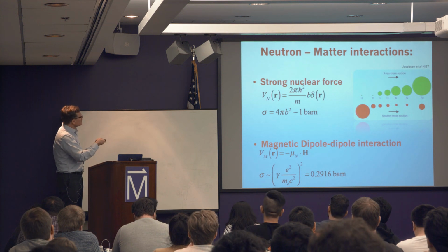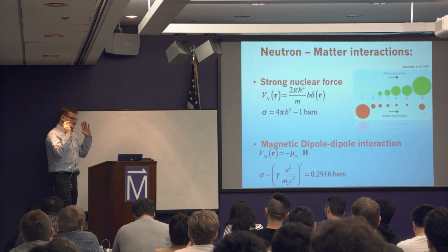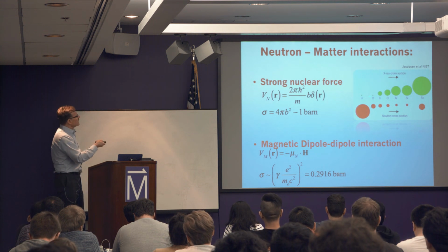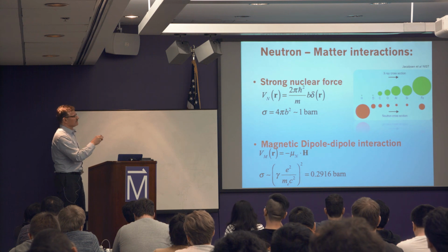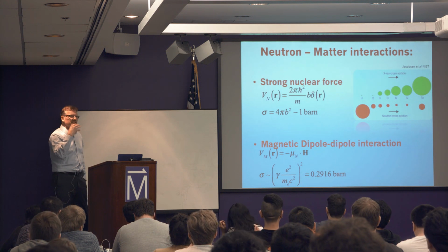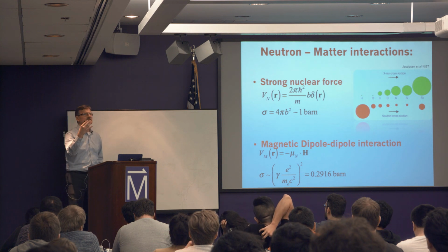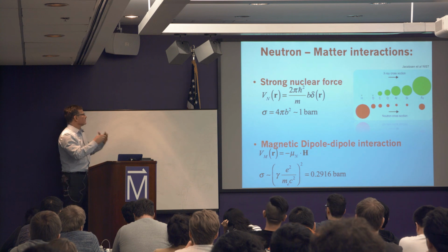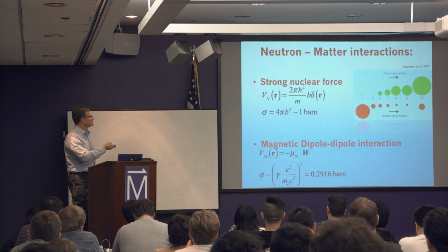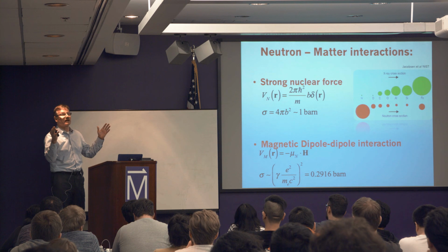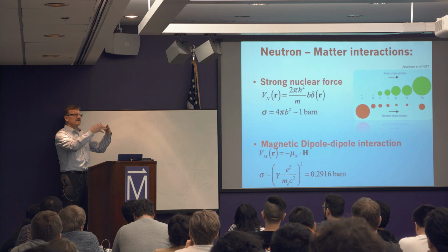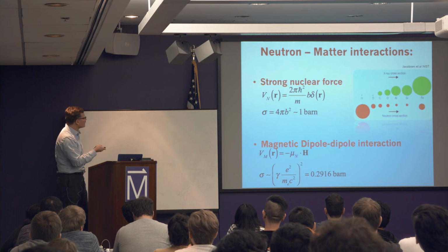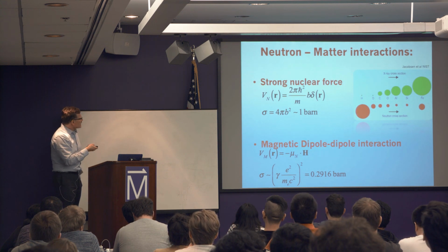And the characteristic parameter that basically encodes the behavior of the individual nuclei varies very dramatically from element to element and from isotope to isotope, and that is actually an advantage for us experimentally, as opposed to X-ray scattering, where the heavier elements always have larger scattering. In our case, sometimes very light elements can have a lot of scattering, so we can see hydrogen inside a heavy matrix quite straightforwardly.